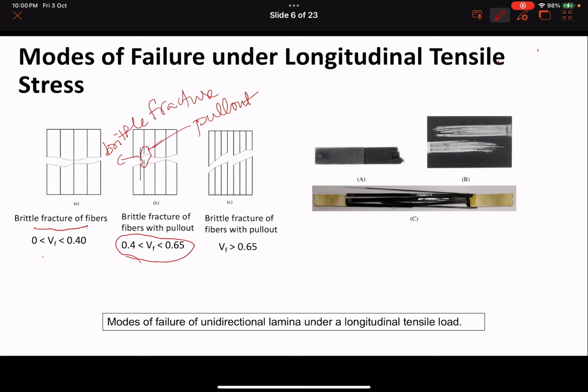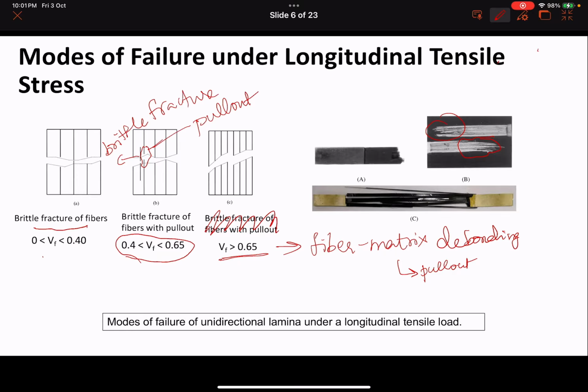But if you have too much fiber, more than 65%, then the resin might not really seep into it, and there might not be uniform distribution. This is wrong. So what will happen in those cases is fiber matrix debonding. And that may also cause pullout. So here in the picture, actually you can see that there's kind of uneven breakage, right? That's also, that kind of shows you pullout and fiber fracture.